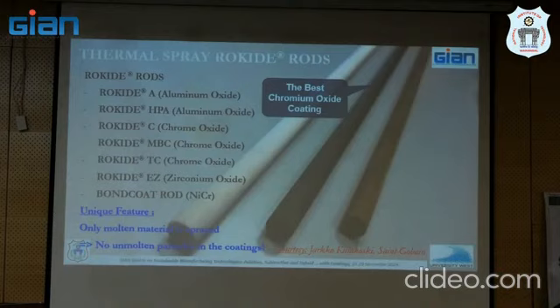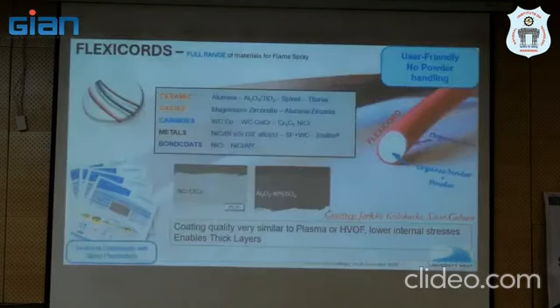One is availability of rods of different composition, not very new, but this synchronizes well with new equipment that allows rods to be fed. We are very excited about this FlexiCord because just 2 weeks back on my way to India, Saint-Gobain launched something called cord plasma spray, and that's a result of all the work that we have done in our lab with their FlexiCords. So it's the first time that we have shown that even using a cord like this with zirconia, you can get columnar structure, right? That's a big thing for us. Nobody's shown that before, right?